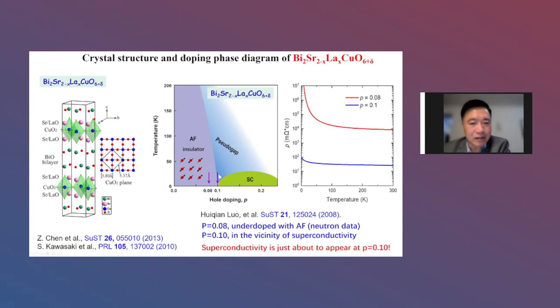Okay, so here we take two special doped samples: one with 8% doping, one with 10% doping. You can see we measured the resistivity of the single crystal samples. The 8% doping shows a very huge and strong insulating behavior. And at 10% doping, the resistivity becomes much lower, but still shows semiconducting behavior. Okay, and please remember that the superconductivity just appears at the boundary of 10%.